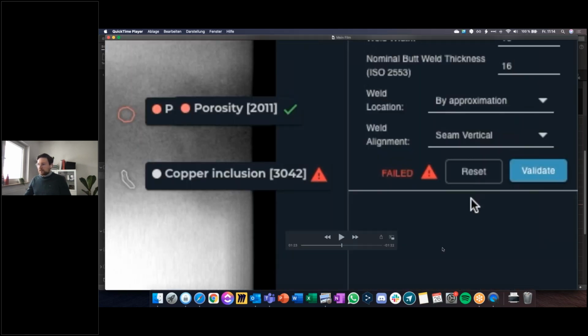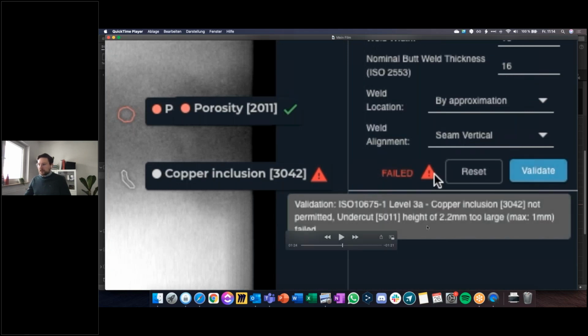Now we have another example for that. Here we have a copper inclusion, and then you get shown that the copper inclusion is not permitted, and you also get the information about the undercut that is too large according to the standard, so it's not acceptable.